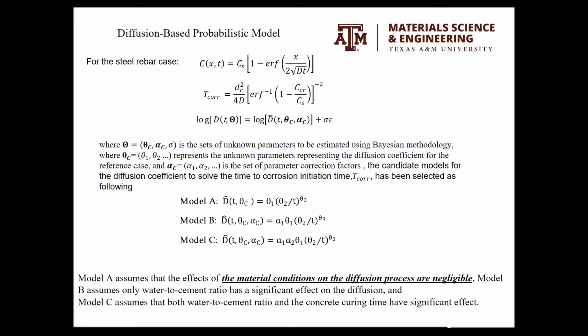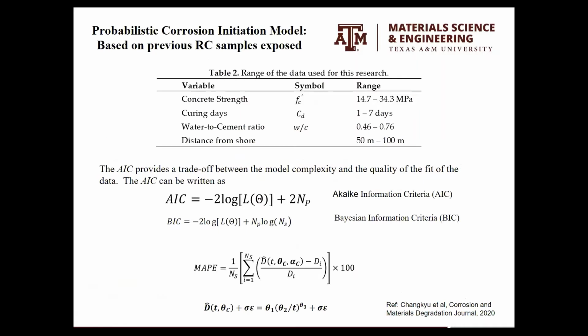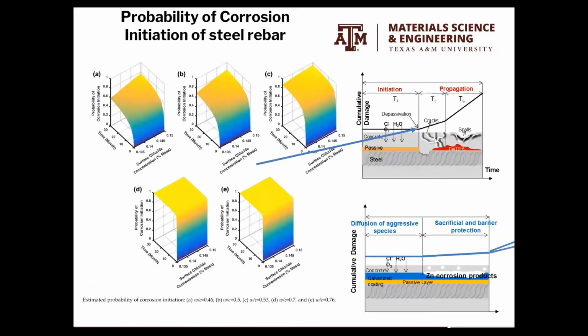assumptions about whether the model is based on the diffusion coefficient or on different parameters, and we set the parameters, models A, B, C, based on different components of the concrete, either the water-cement ratio, current days, distance of a source of chlorides. So we did that, and we have this reference, we report this. And this is the probability of the initiation time, the initiation based on the characteristics of the concrete.